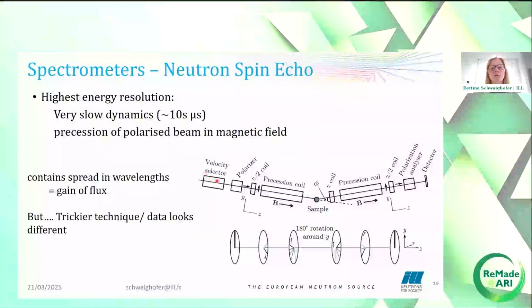The neutrons then move through a first magnetic field where they start to precess. They then hit the sample, after which there is a second equivalent magnetic field, but pointing in the opposite direction effectively. And therefore, if there is no energy transfer, the polarization of the neutrons is fully regained. However, if the neutrons lose or gain energy at the sample, the times spent in the two magnetic fields are not equivalent, and the polarization will decrease. And this is what is measured in neutron spin echo spectroscopy.